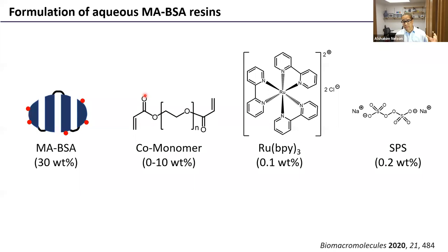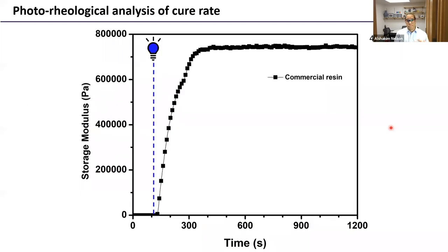Okay, so we can achieve low viscosity resins with MABSA, but we do have to co-formulate it with a few things in order to make a printable resin. So this is an aqueous-based resin, so it is in water, but we co-formulate with a bit of PEG diacrylate. I'll get to why in a second here. We use a ruthenium complex as a photocatalyst, just a small amount, and then we use SPS as our radical generator. So now, we use a photorheometer to track the rate of photocuring.